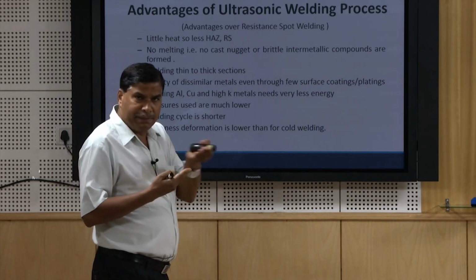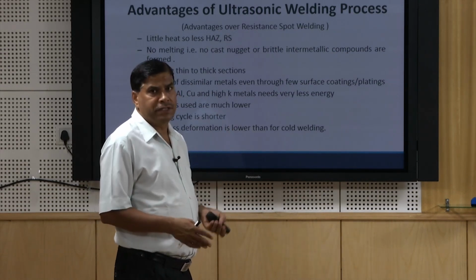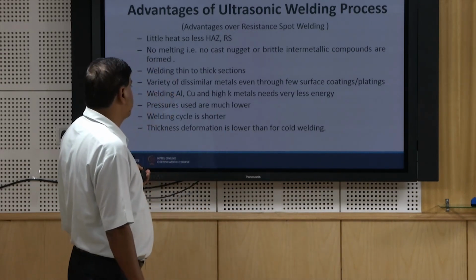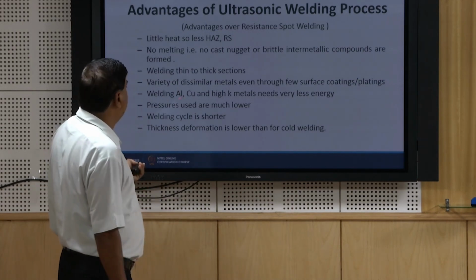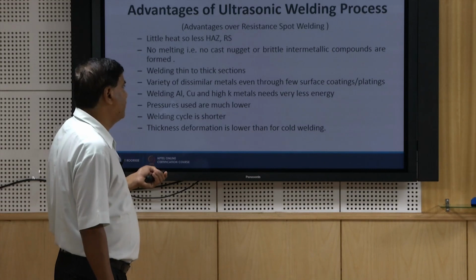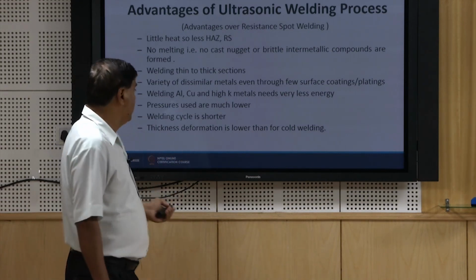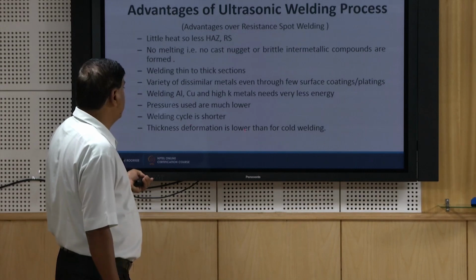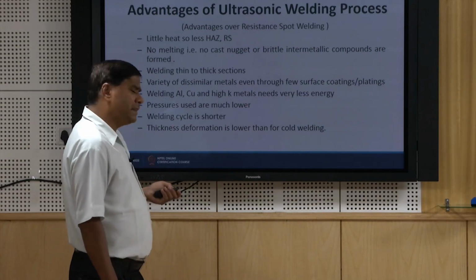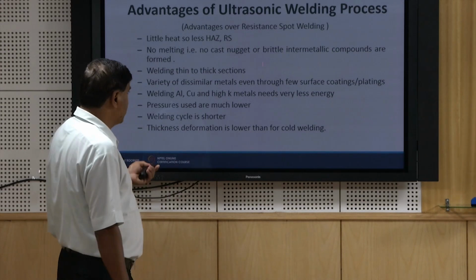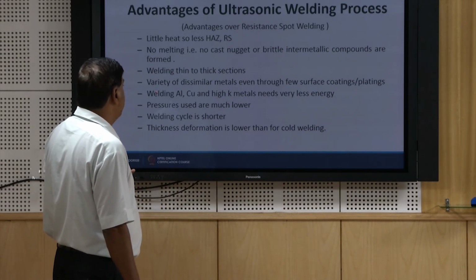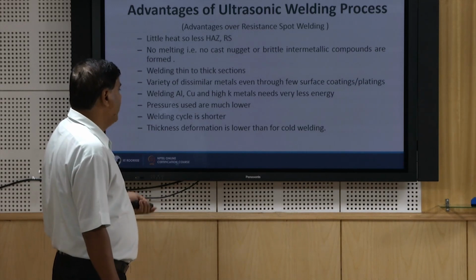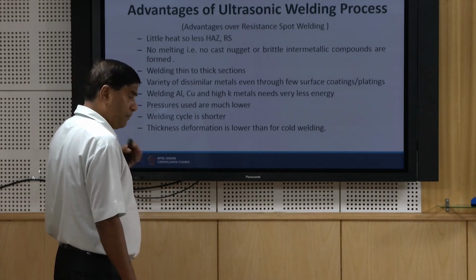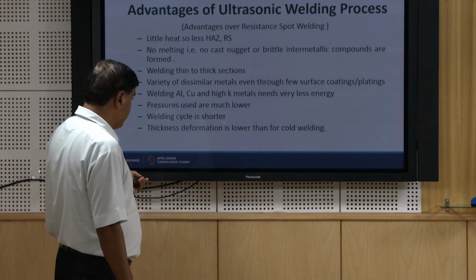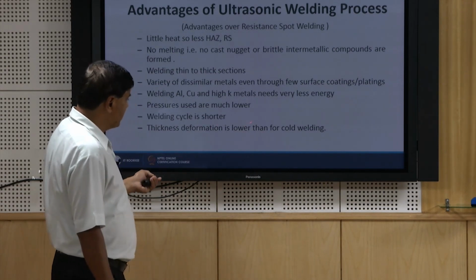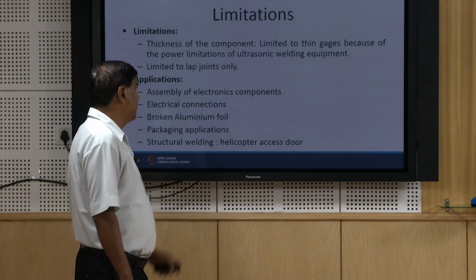So, if the base metal is coated, then through the coatings also the joint can be made by the ultrasonic welding process. The amount of energy required for welding aluminum and copper is much less as compared to that required for resistance spot welding. Similarly, the weld cycle time is very short, and the pressures applied are much lower as compared to those used in resistance spot welding for joining aluminum, copper, and other high electrical, high thermal conductivity metals. So, thickness deformation in this case is also very limited as compared to the cold welding process.